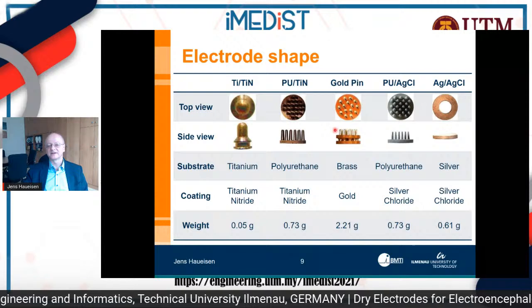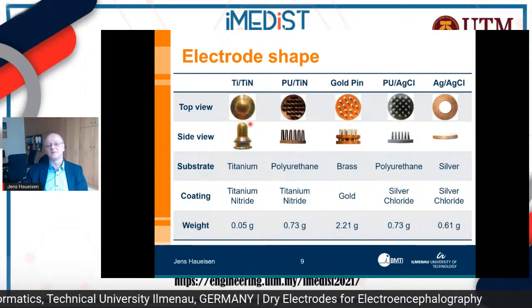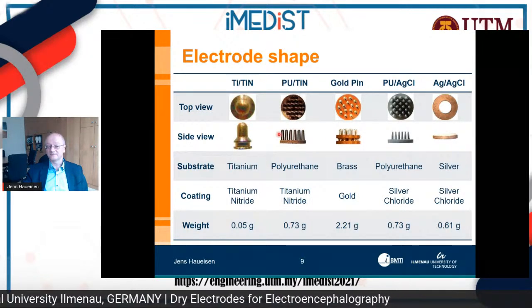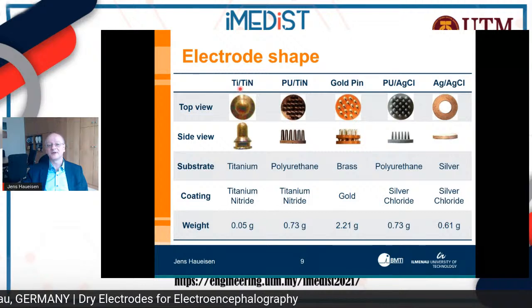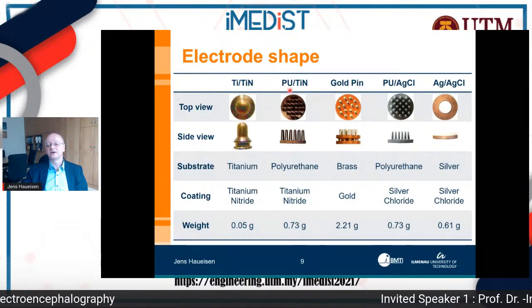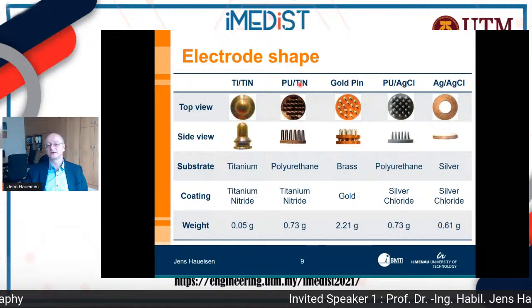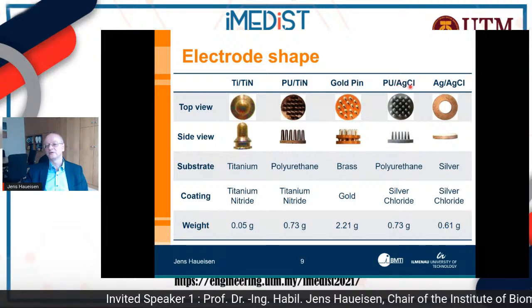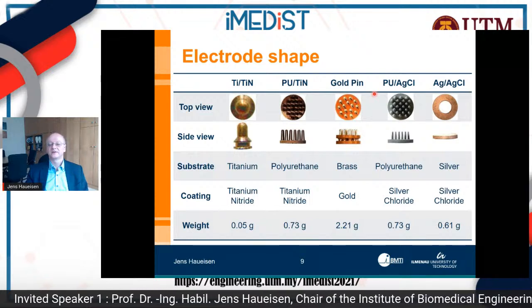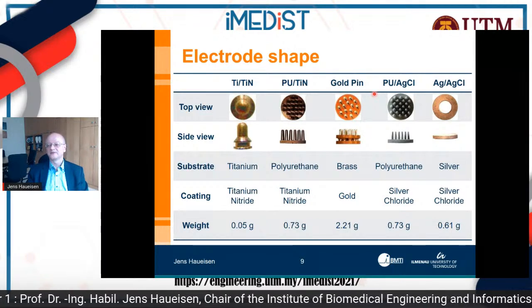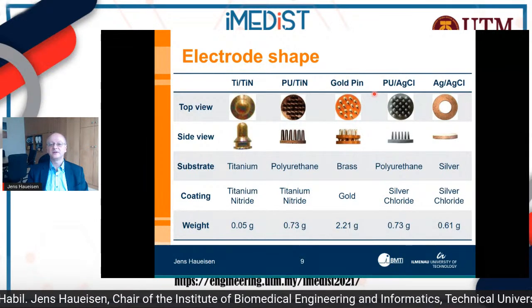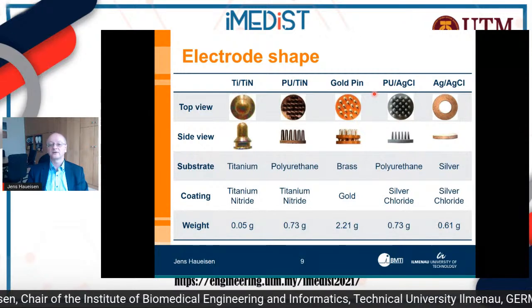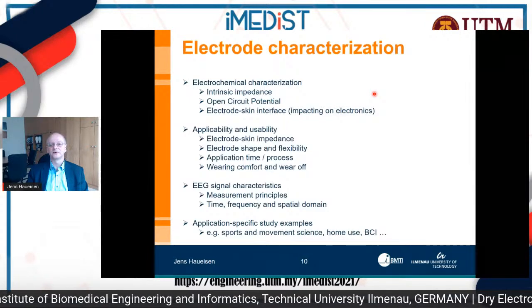And this is something which we tested and characterized. What you can see up here is that we used quite different materials: titanium, titanium nitride, polyurethane coated with titanium nitride, gold pins, polyurethane coated with silver chloride. So they're quite different in terms of materials, and that means you need to characterize them. And this is what I want to show you in this slide.